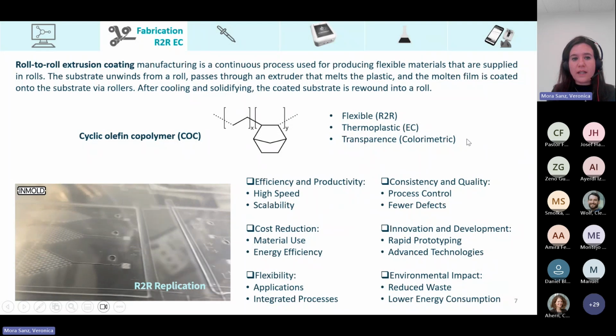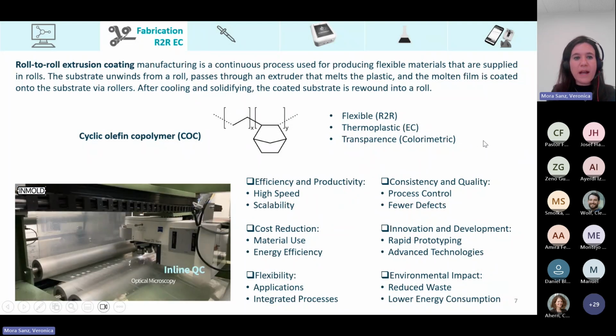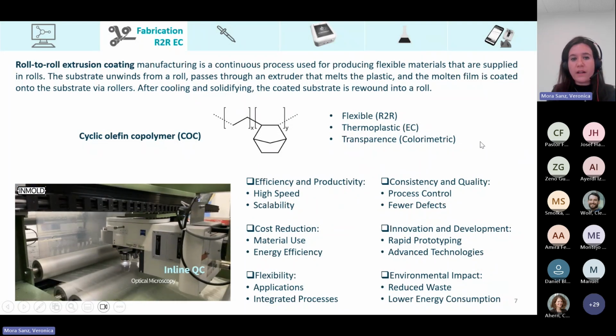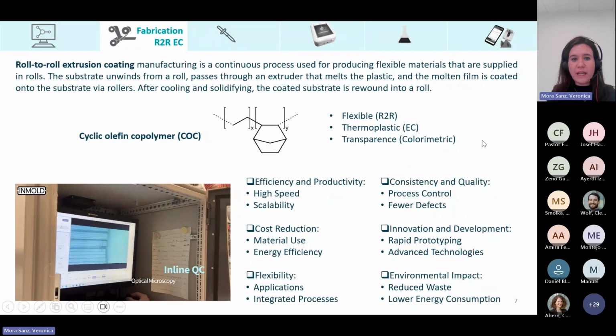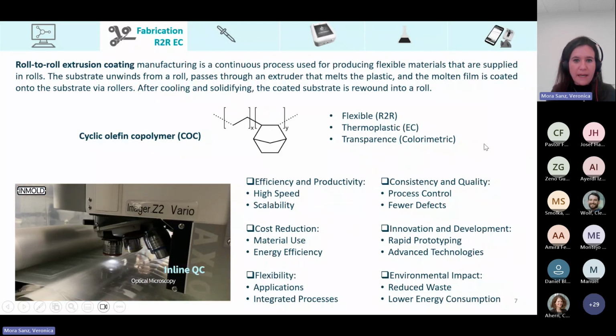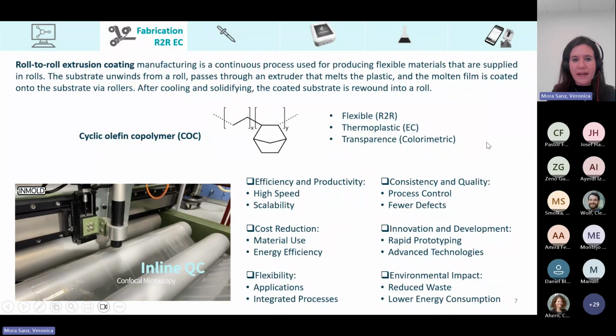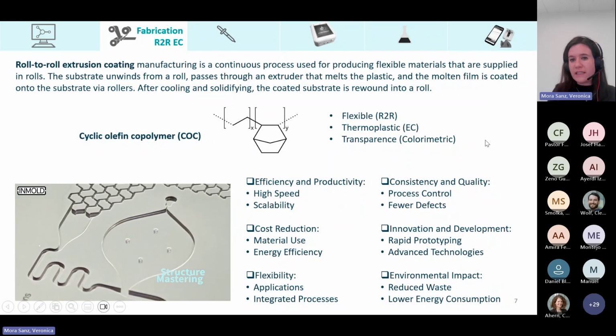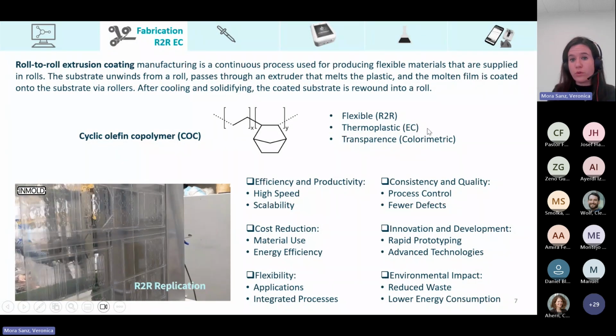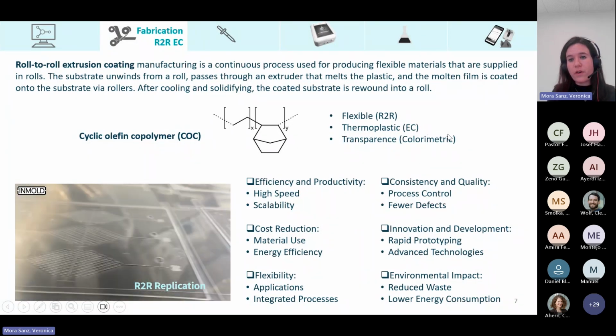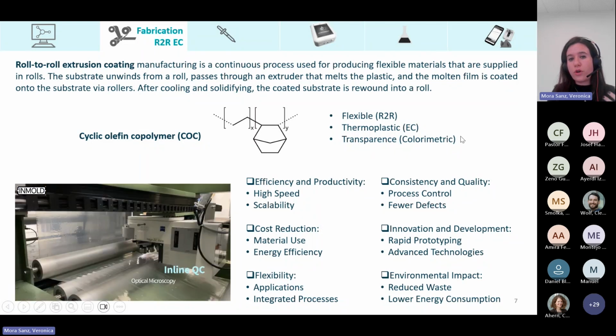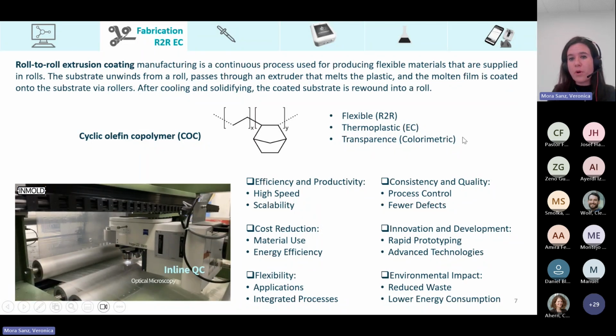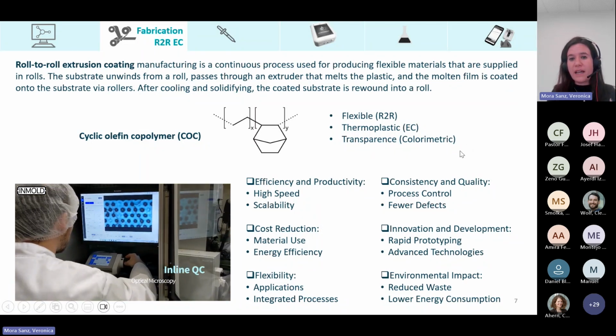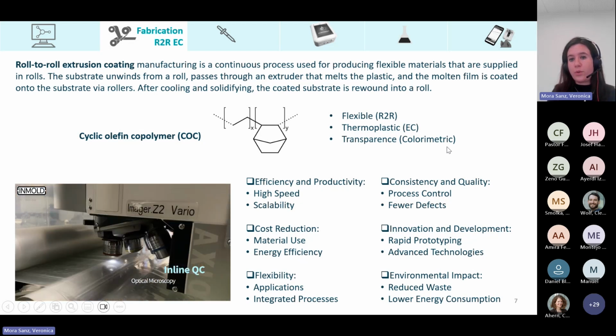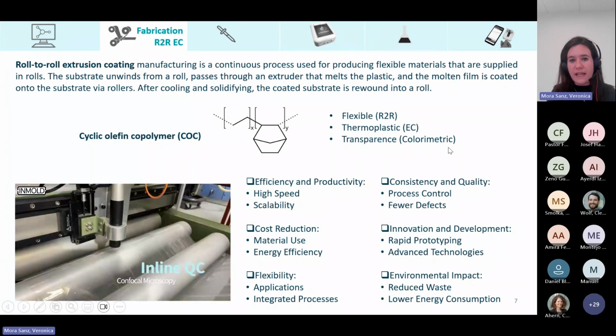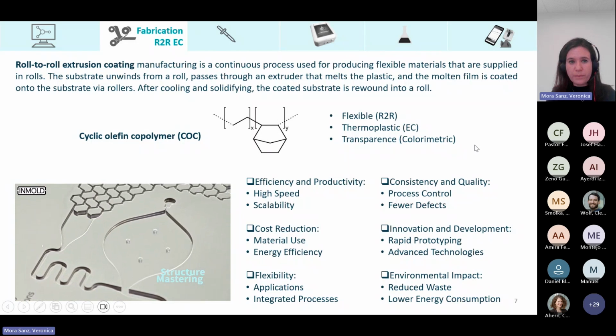We decided to employ this material, cyclic olefin copolymer, COC, because it met all the required criteria that we needed. It is flexible, required for roll-to-roll, thermoplastic for the extrusion coating, and also due to its optical properties, because we need the chip to be transparent to be able to measure this colorimetric reaction.